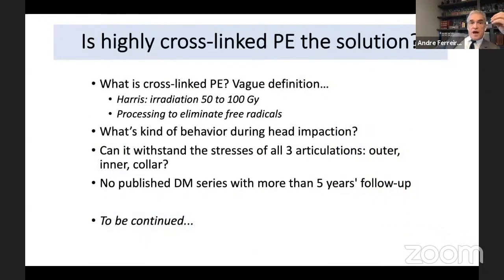So now the question is, is highly cross-linked polyethylene the solution, maybe better than the standard polyethylene? Yes, but what is cross-linked polyethylene? It's a very vague definition given by Harris. It is due to irradiation from 50 to 100 grays with a process to eliminate free radicals. But what kind of behavior occurs during head impaction? Can it withstand the stress of all three articulations? You remember the three: the outer between the insert and the metal-back shell, the inner between the head and the insert, and the collar, the rim of retention.